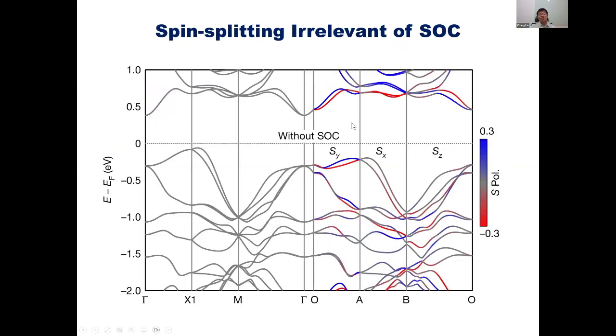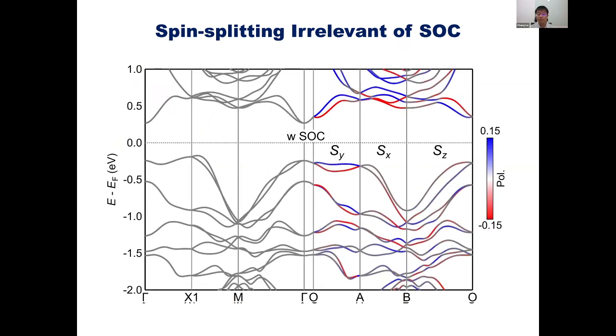So the spin splitting here is irrelevant to the SOC. We can see that without the SOC, it already has a very large spin splitting. With the SOC, the spin splitting just shifts a little bit instead of enlarging or shrinking. So with and without SOC, this compound has spin splitting that is induced by AFM order.